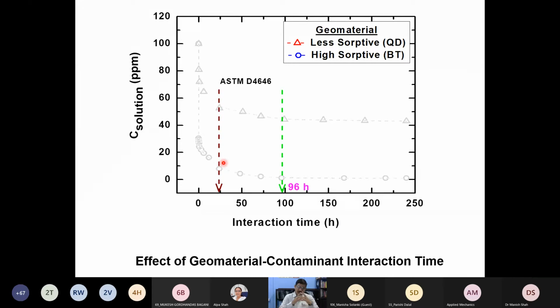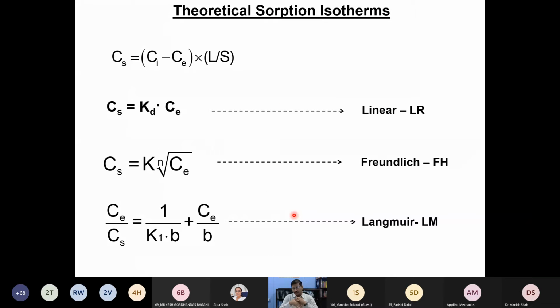So what we did is, in order to get the equilibrium interaction time, what time do you need? It depends on the nature of the material. For example, in case of a geomembrane, in a quick test, you may be able to achieve uniformity within a short period of time. Meaning, you take a contaminant, for example 100 ppm in the solution, you put a soil in it or maybe the geomembrane in it, and then you try to see how the solution concentration is going to vary with respect to time. Over a period of time, what we have noticed is that around 96 hours is really good enough. So the remaining tests, we conducted using 96 hours of interaction time.